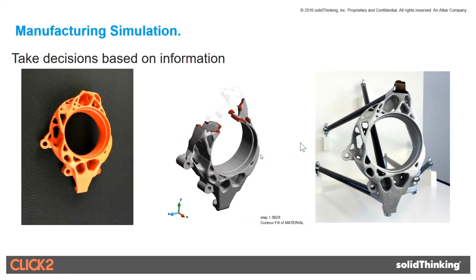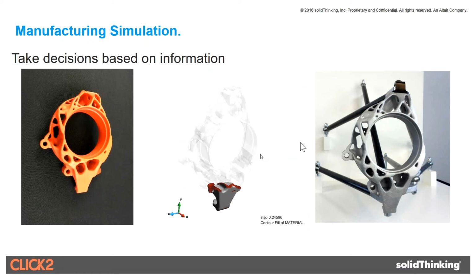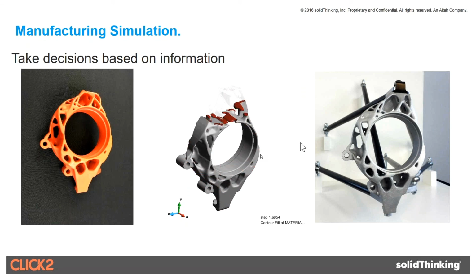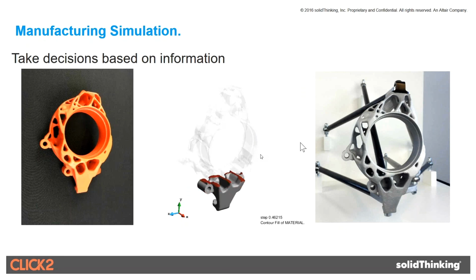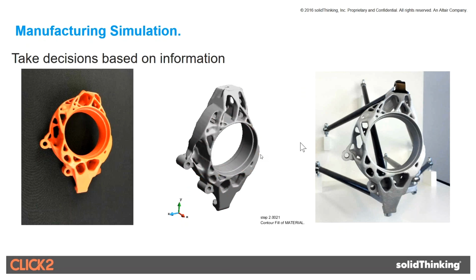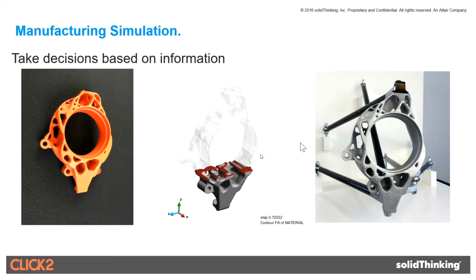And we did identify a couple of areas where there could have been porosity, but the porosity is very, very small. So if you summarize it, we took the original design, and what we did was we 3D printed the pattern. And the investment casting process, if you do not understand the process, I'll just take a second to explain that.